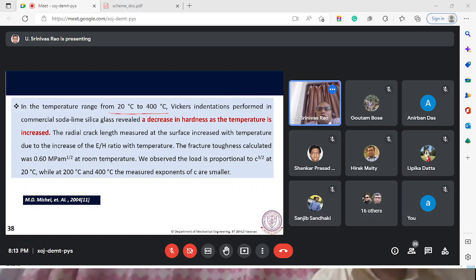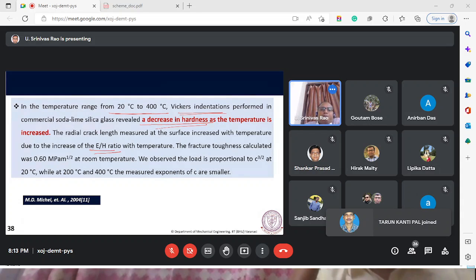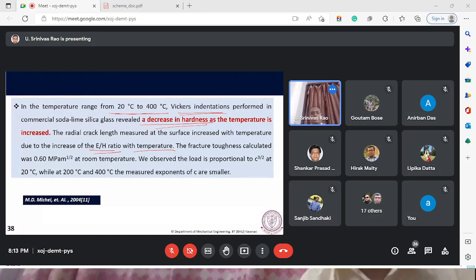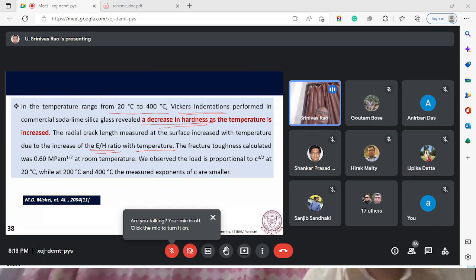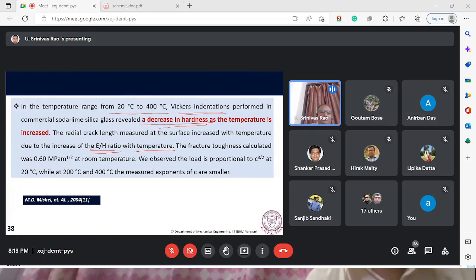So in this range, through these Vickers indentation experiments, it has been observed that the hardness decreases as the temperature increased. And the radial crack length measured at the surface increased with temperature. So these experiments give an idea that if we can increase the temperature of the specimen, then there is a possibility, because the E by H ratio is important for the DC. In that Bifano model, we have one term which is E by H. So if H reduces, this DC will increase. So that is the effort.